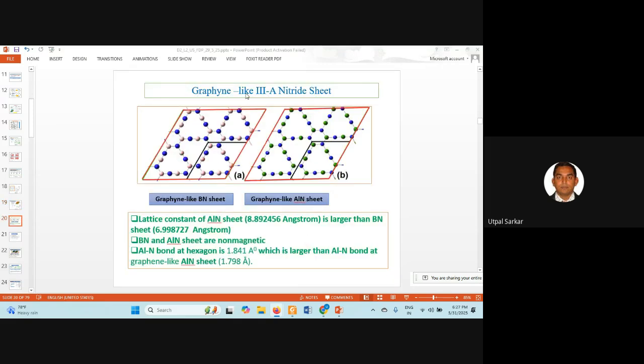Some other, like aluminum nitride and boron nitride sheet, we have compared. So here it is aluminum nitride, a boron nitride like sheet we have already discussed. A comparison between these shows that the lattice constant of aluminum nitride is larger than the boron nitride sheet, and BN and AlN sheets are basically non-magnetic. The aluminum nitrogen bond length at the hexagon is 1.84, which is larger than the aluminum nitride bond in the graphene-like aluminum nitride sheet. So you can make the comparisons, and the lattice structure you can also calculate through quantum chemical calculations for these periodic systems.